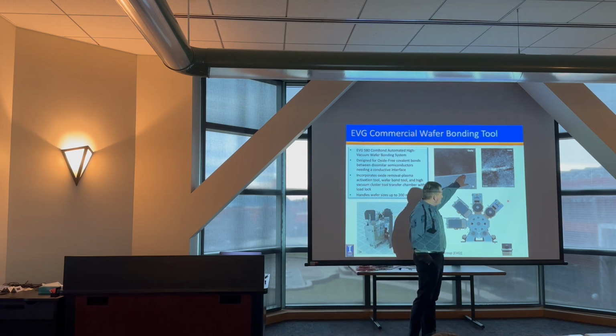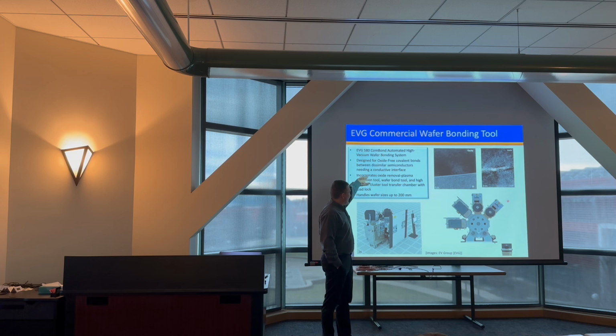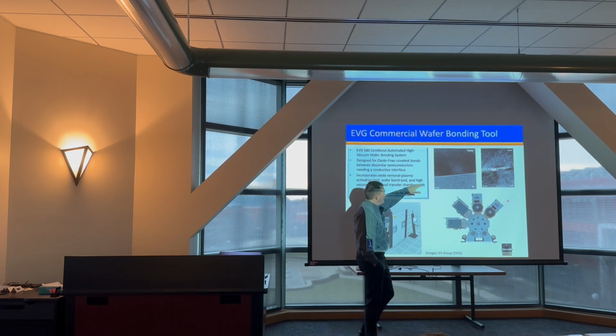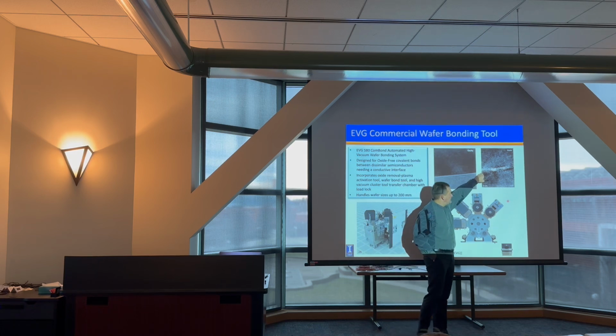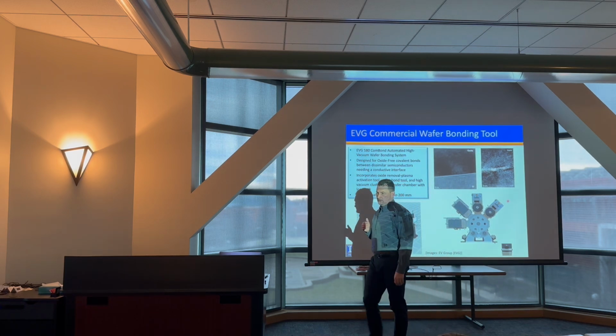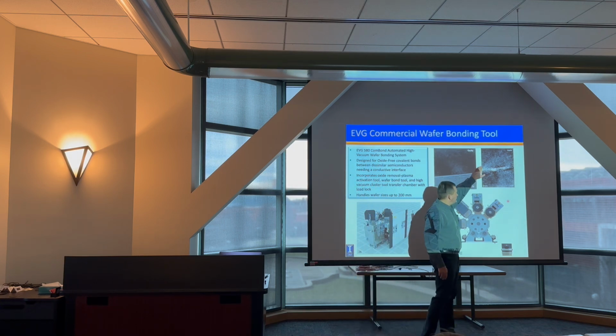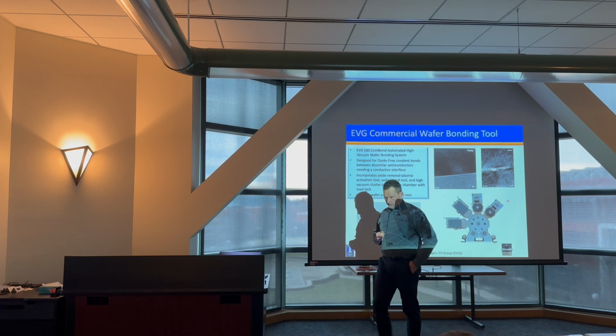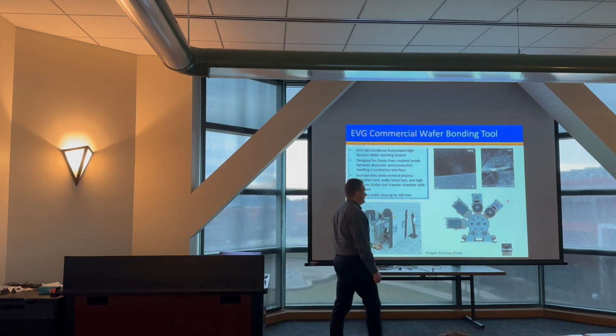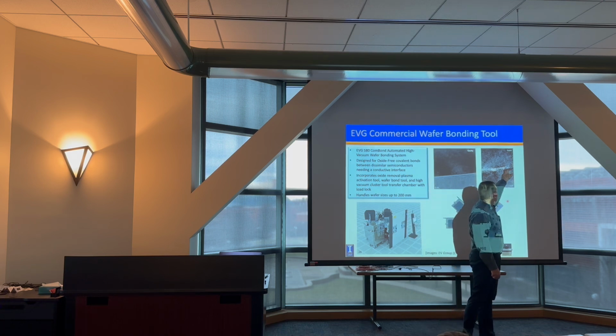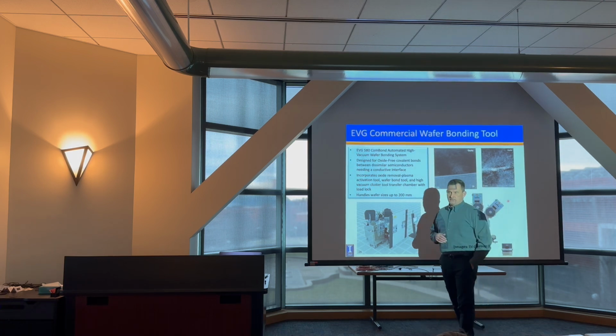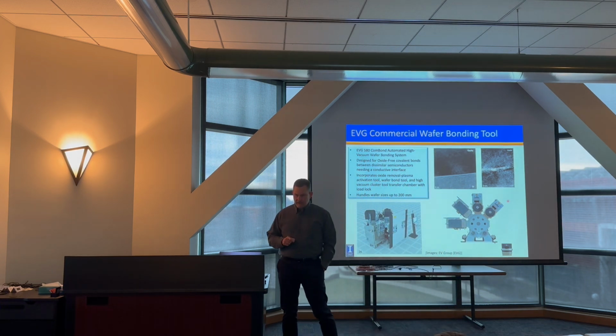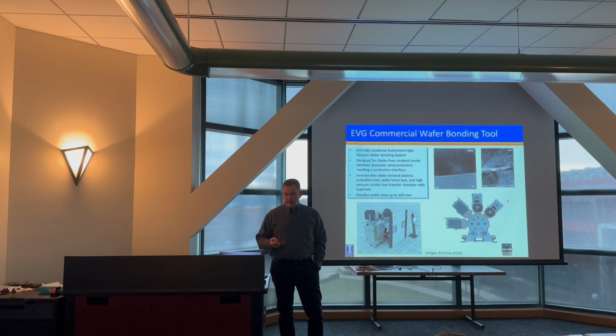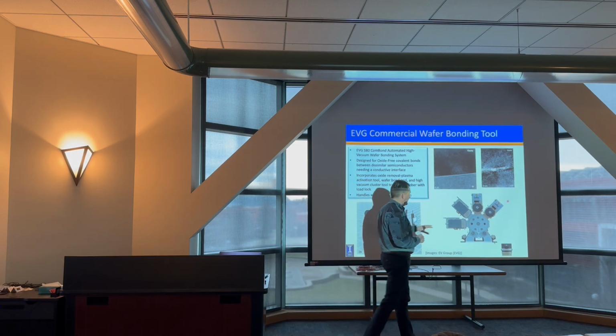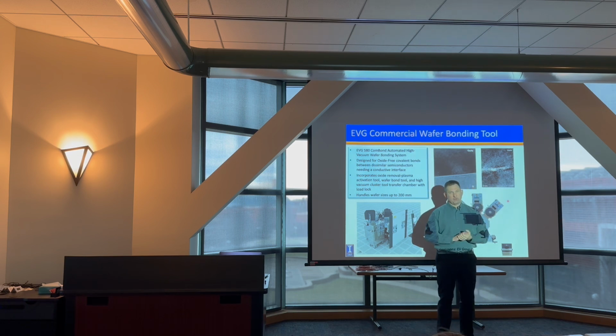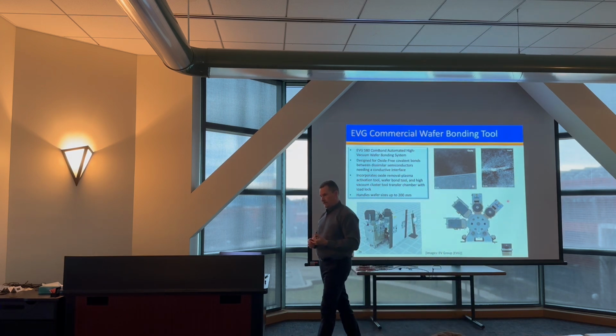But the key thing with these tools is that by the combination of oxide removal using a plasma process and then bonding at a slightly higher temperature, you're able to produce pretty good interfaces between a III-V material and other materials like silicon. Well, this is gallium arsenide phosphide, and people have also done it for silicon and other materials as well. But it is still not a perfect interface, right? This is going to have slightly different optical loss characteristics and also electrical characteristics that may not be perfect. In fact, when people are doing this process, a lot of what they work on in optimizing their parameters is trying to improve both the electrical properties of the interface and optical properties.